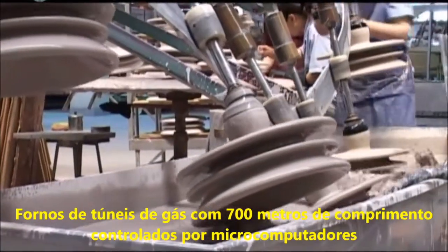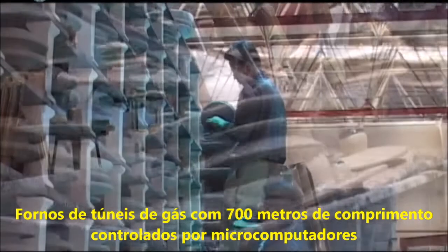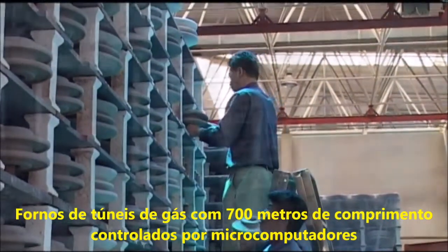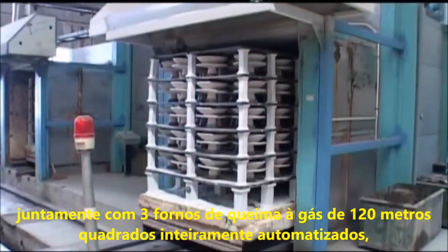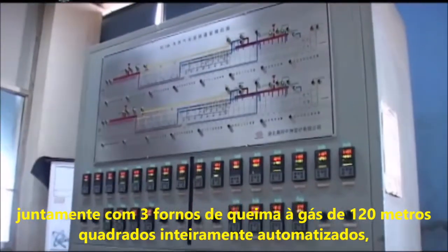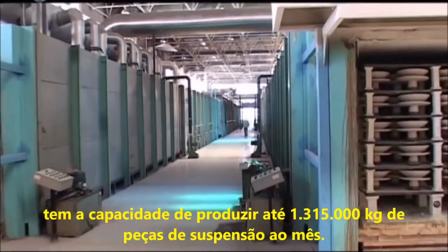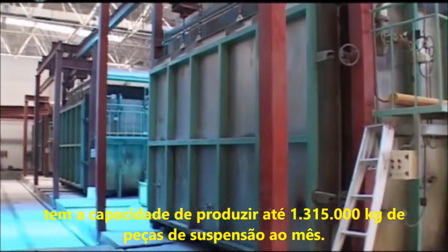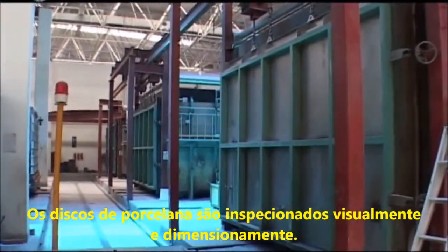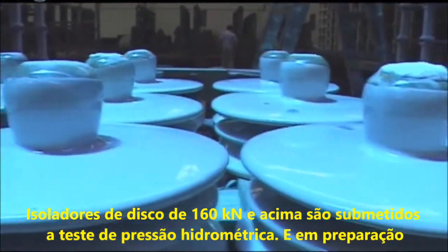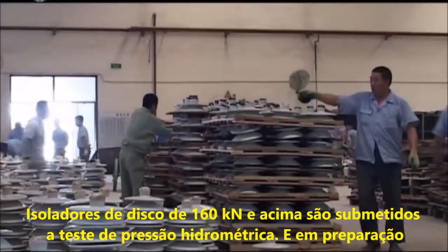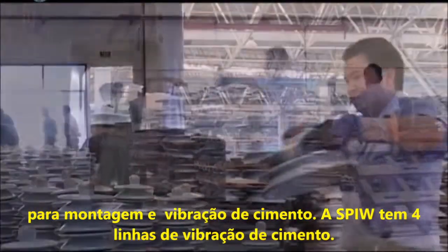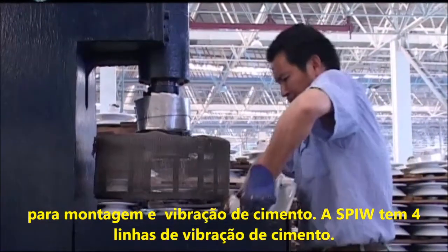2 2,300-foot fully automated microcomputer-controlled gas tunnel kilns along with 3 1,300-square-foot fully automated microcomputer-controlled gas shuttle kilns can produce up to 2.9 million pounds of suspension pieces per month. Porcelain discs are inspected visually and dimensionally. 36,000 pounds and above discs are subjected to hydraulic pressure testing in preparation for assembly and vibration cementing.